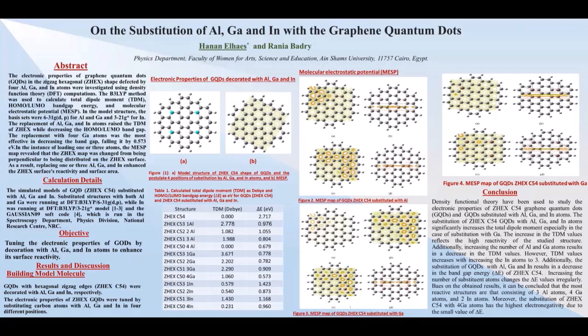The conclusion: density functional theory has been used to study the electronic properties of the proposed structure of zigzag hexagonal graphene quantum dots consisting of 54 carbon atoms and graphene quantum dots substituted with aluminum, gallium, and indium atoms. The substitution of Z hex graphene quantum dots with aluminum, gallium, and indium atoms significantly increases the total dipole moment, especially in the case of substitution with gallium. The increase in the total dipole moment values reflected the high reactivity of the studied structures.